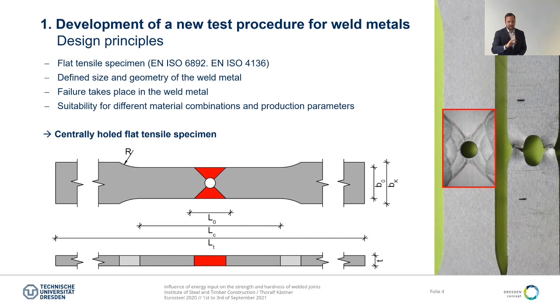And of course, the test specimen should be suitable for different material combinations and production parameters, so that we can cover both undermatching welds, where the weld metal strength is lower than that of the base metal, but also overmatching welds, where the failure usually should take place in the base metal, but as we wanted to determine the weld metal strength, the failure needed to take place in the weld metal. And therefore we decided to use a centrally holed flat tensile test specimen, where we have a defined size and geometry of the weld and also a controlled notch factor at the weld seam.